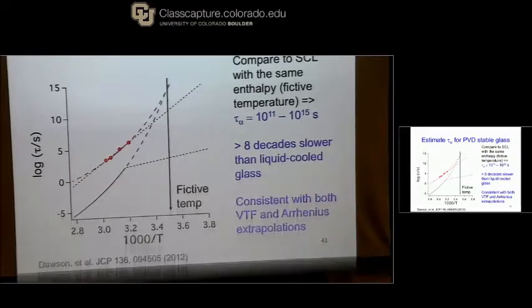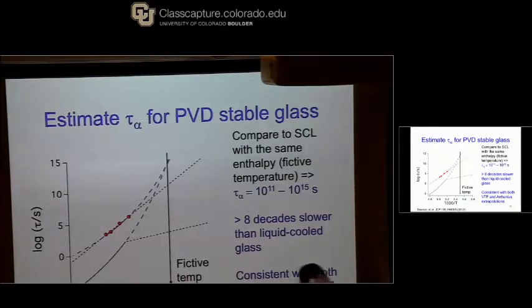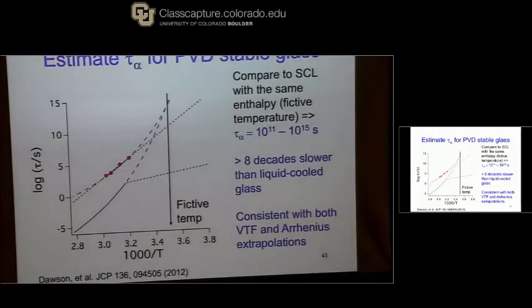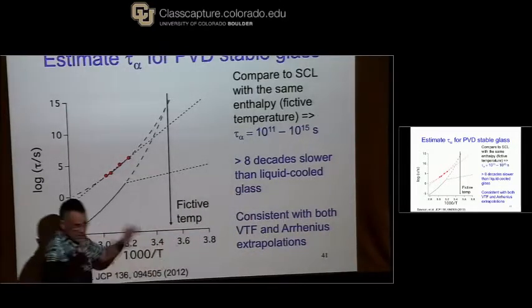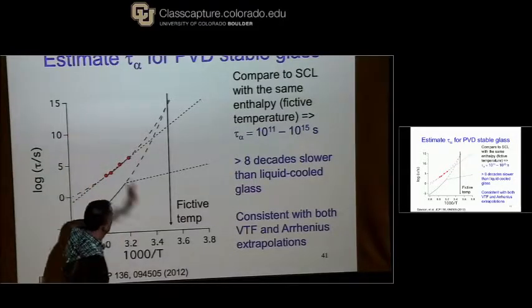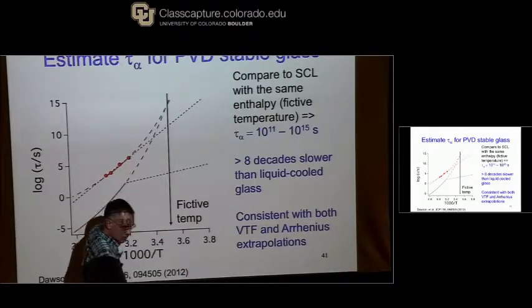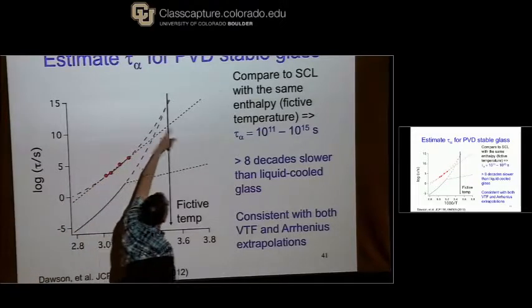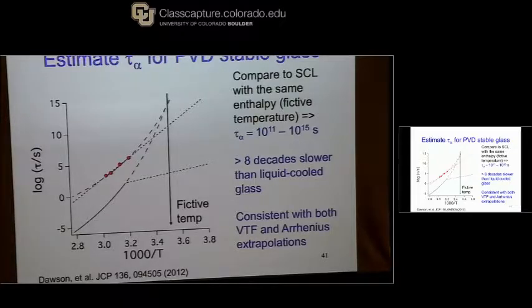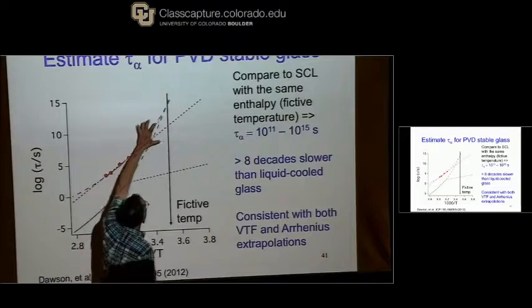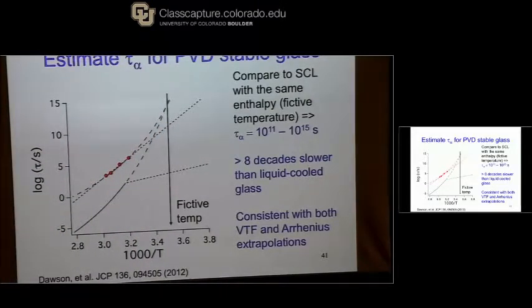And then I know what the enthalpy of my glass is. And I'm going to use that enthalpy to figure out what temperature I should plot my vapor deposited sample at for this comparison. And so if you're used to the language of fictive temperatures, I'm comparing the supercooled liquid and the vapor deposited glass at the same fictive temperature. Okay? So this kind of calculation, which has some approximations in it, clearly, says that we would expect at this temperature the structural relaxation time for this material to be somewhere between 10 to the 11th and 10 to the 15th seconds. Okay, so it sort of makes sense that we didn't see much happen in 10 to the 5 seconds because it's a really long time. Those estimates on the upper end are consistent with this diverging function, and they would also be consistent with other functions. Okay, so that's what we can say.